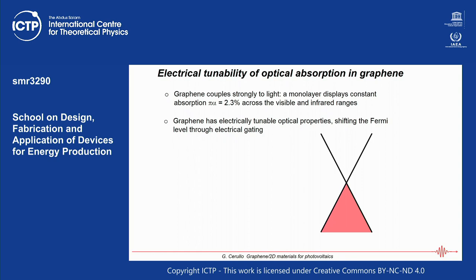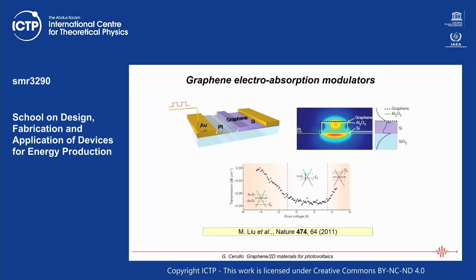In intrinsic graphene, the valence band is completely filled and the conduction band is empty, so I can promote electrons with photons of arbitrary energy and absorb at any wavelength. But if I apply a gate and shift the Fermi energy — for example depleting the valence band of electrons — graphene can no longer make these transitions and becomes transparent. I can very easily switch graphene between absorptive and transparent states electrically, controlling its optical properties very quickly, which is ideal for optoelectronics and optical modulation.